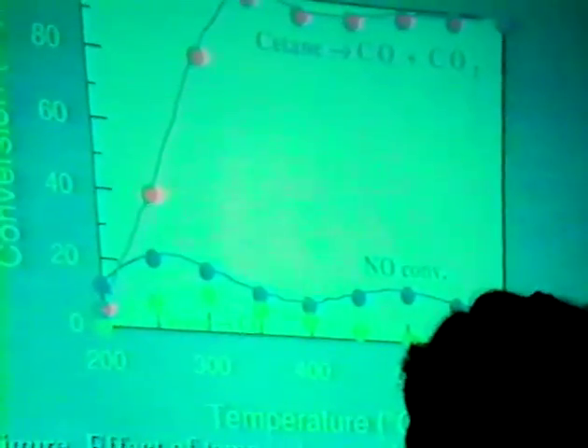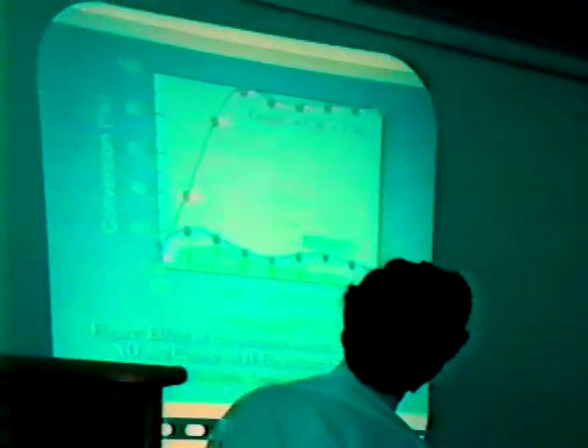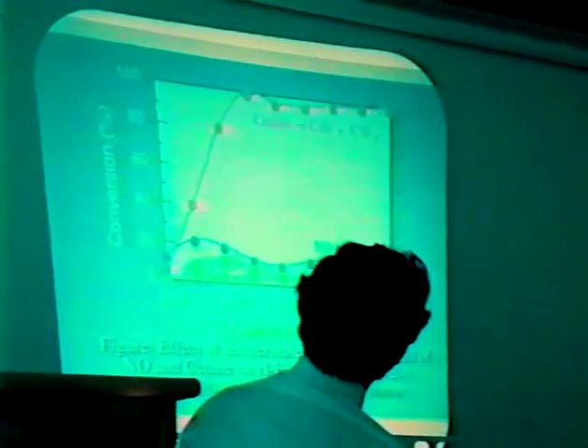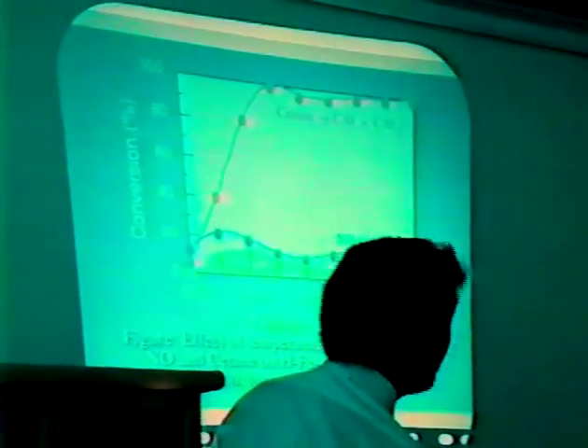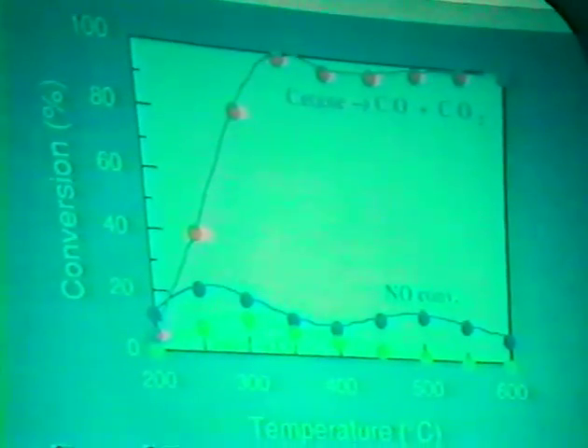This is iron-containing metal silicate. In this case, cetane can combust at very low temperature and attains almost 100% combustion into complete combustion products. Then for NO, if hydrocarbon can combust too easily, this has almost very small effect on NO conversion. Because maybe most of the hydrocarbon too easily combusts at the entrance of the reaction zone. If we modify it partly by platinum, of course cetane conversion shifts to lower temperature side, but it's more productive overall.